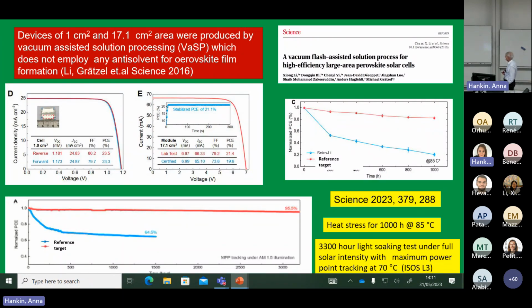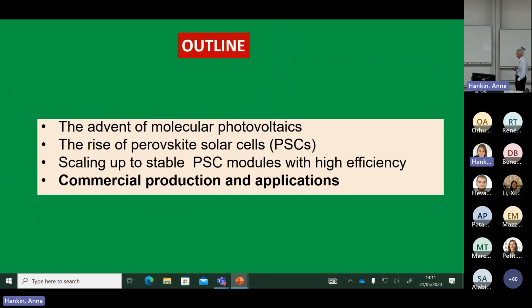And so you see today these systems have 3,300 hours and less than 5%. That's at 70 degrees, maximum power point tracking. And so that's a challenging condition. You keep your cell on the maximum power point, full sunlight for 3,300 hours, and that's about half a year, or at least 4 months. And then keep temperature up, combined heat and light stress, and you get less than 5%. That looks good. So we can think about scaling this up and putting it outside in the sun.